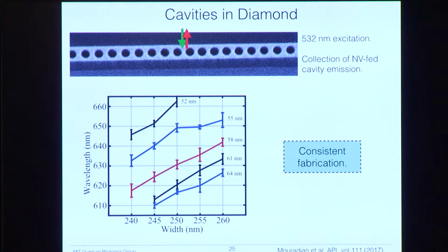The other thing, of course, about fabrication is you don't only want to make one hero device. You'd like to be able to make many devices on the same chip and have them all work out. And so we measured all the devices on the chip. We made a couple with many different parameters. So we changed the width, and we changed the hole diameter. And we see that we have very nice scaling. As the width increases, our resonance wavelength increases as well. And the opposite for the hole diameter, which is what we expect.